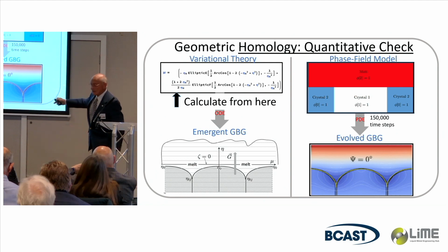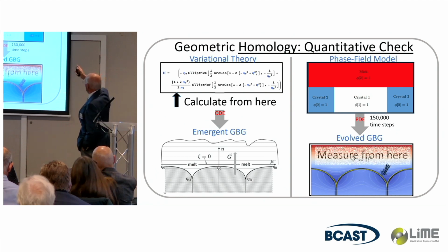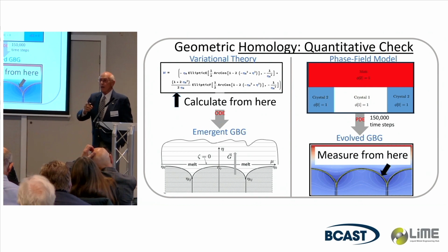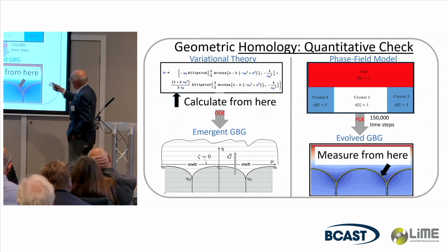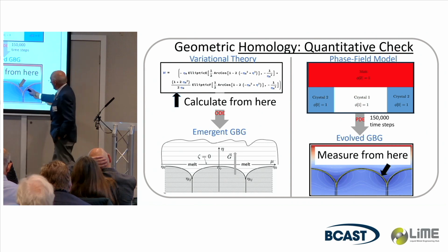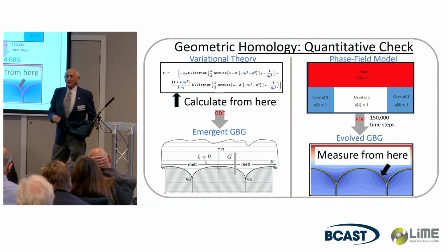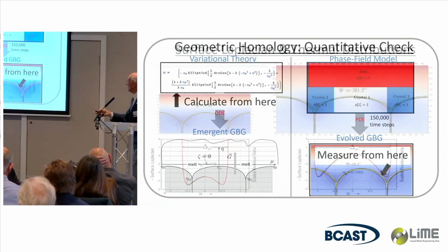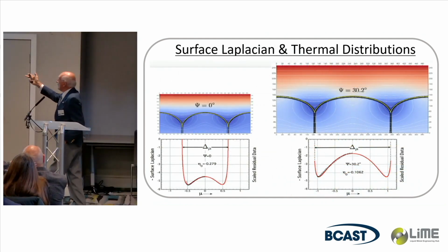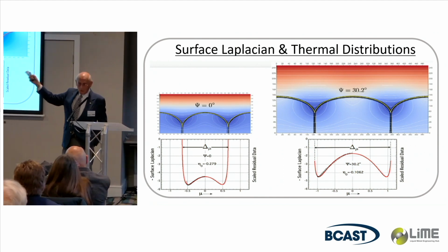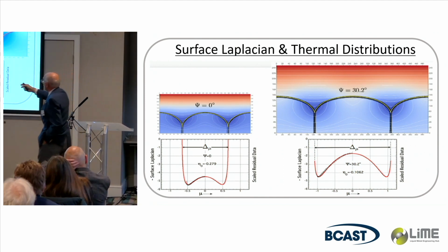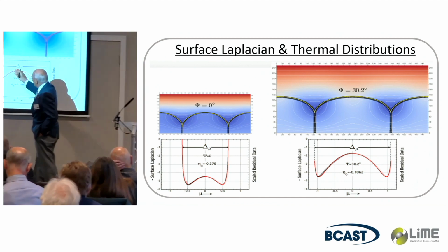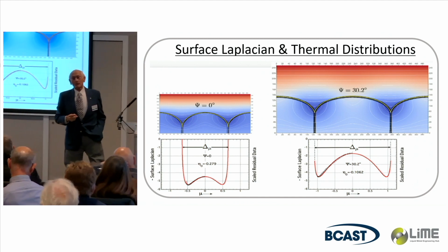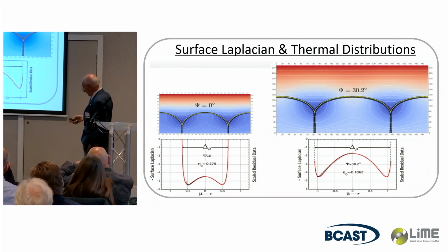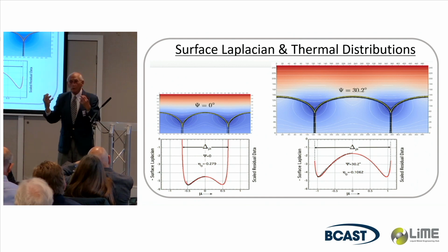From this identical counterpart, we go ahead and measure using essentially post-processing measurements. You actually measure the chemical potential very accurately on the interface. And finally, here's the results. The surface Laplacian, which is what we calculate from the variational ones, gives essentially almost exact fits to our measurements. What's very interesting, those blue areas is where cooling is occurring.